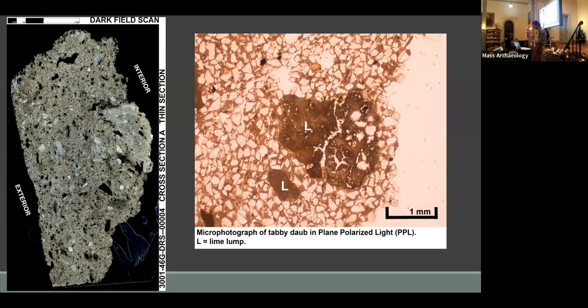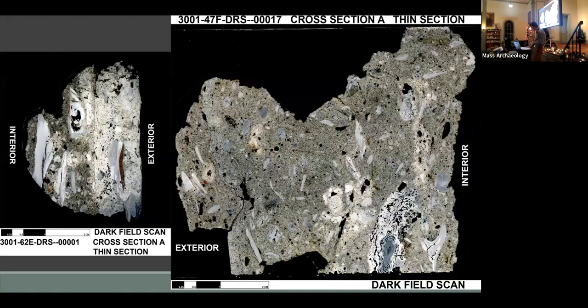And because, depending on its porosity, lime mortar can take months or years to attain its ultimate strength. What's interesting is that in a lot of these examples, the lime binder is quite heterogeneous, with samples displaying what I describe as a mottled texture. These binders appear to have identical aggregates, so they are the same material, but under the microscope, the lighter areas appear more amorphous or micritic, while the darker areas appear more crystalline or microsparitic, for you geology folks, indicating different geochemical reactions as the binder sets and undergoes carbonation.